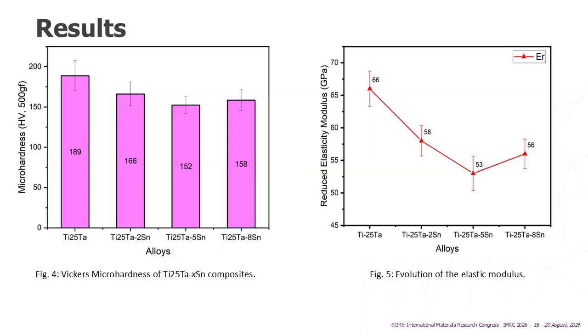Likewise, the slightly higher values in the titanium 25 tantalum 2 tin with 58 GPa and titanium 25 tantalum 8 tin with 56 GPa result from incomplete stabilization with residual titanium alpha phase and the solid solution hardening effect of tin atoms in the titanium beta lattice.